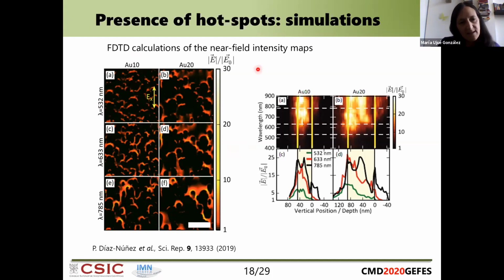And this increase in enhancement with the increase in wavelength, we understand because in this case we have very strongly interacting plasmons between the different nanocolumns, because they are very close one to the other. And so this makes that we have a redshift of the behavior. And well, here this is a more compact plot of the position of the field enhancement regarding the wavelength. Here you can see the wavelength, and the brighter points are the ones where we have higher enhancement, of course. So you see that in both cases, in short and long nanocolumns, the enhancement is bigger for bigger wavelengths.